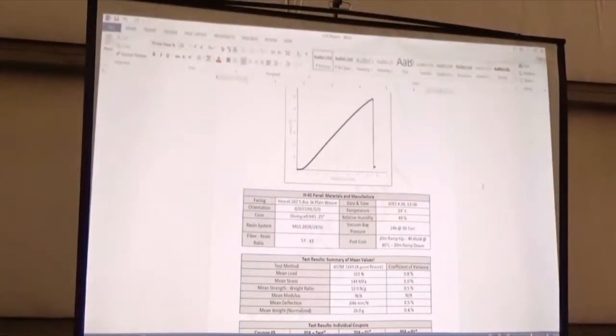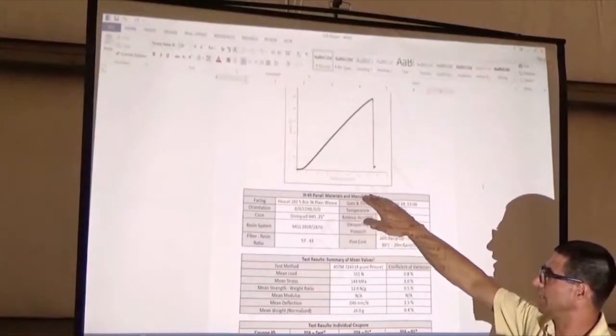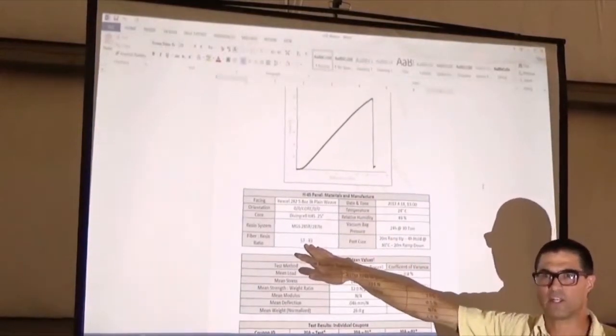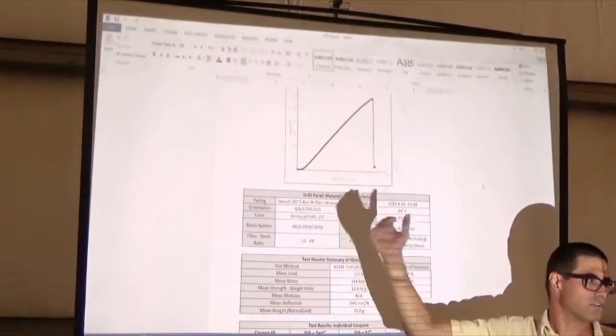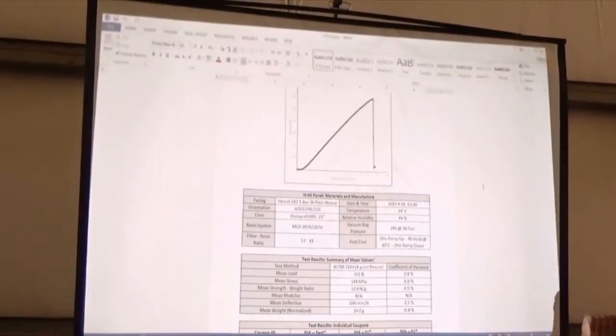For all of these coupons, when we fabricate them and when we test them, I write down all of the information of what we're doing. Some of it might be relevant, some of it not, but you just want to keep tabs on all of your data in case you think something might be important, and later you can go back and see. One of the things I look at is fiber-resin ratio. I'm always trying to shoot for about 60-40. Much higher than that, then I get a little bit concerned about dry spots, because this is all hand-laid wet layup.